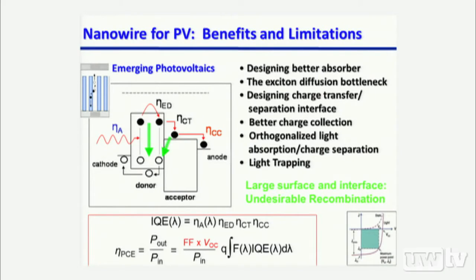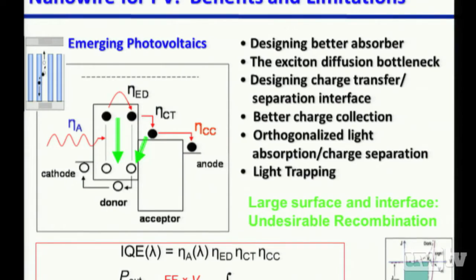But in the end, most of these nanostructure solar cell designs have one common feature, which is a high junction area, okay? Which is very different from the conventional PV design. And this high junction area feature within these nanostructure solar cells introduces one big problem, which has to do with charge recombination. Okay? And that is very hard to overcome within these high junction area solar cells. And that directly leads to the IV performance: typically in the nanostructure solar cell, the fill factor is very low. VOC is lower compared to the more traditional versions of thin film or single crystalline PV. Okay? And that explains why, in many results based on these nanostructure solar cells, the overall efficiency is typically quite low compared to the more traditional version of the solar cell.